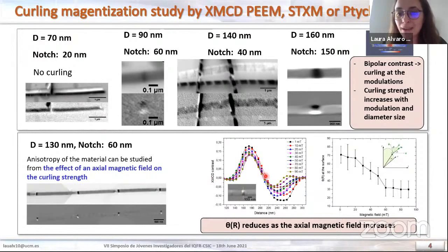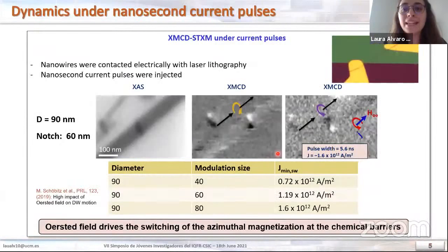So we can see that the magnetic contrast decreases as we increase the magnetic field. And then by using a code that we have developed in the lab, we can have access to the curling angle at the surface of the nanowire and see how it decreases as we increase this axial magnetic field. Then the second approach that we took is applying nanosecond current pulses. To do that, first we contact electrically in the clean room the nanowires by using a process based on laser lithography. And then we are going to apply current pulses.